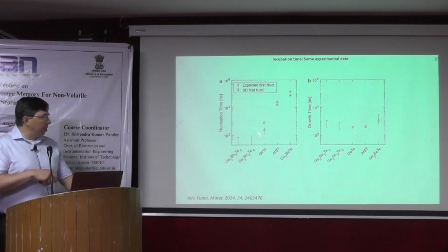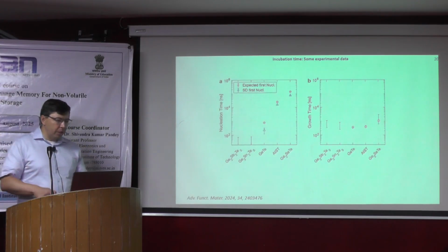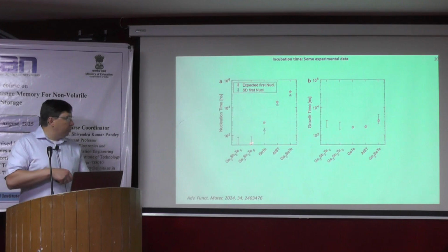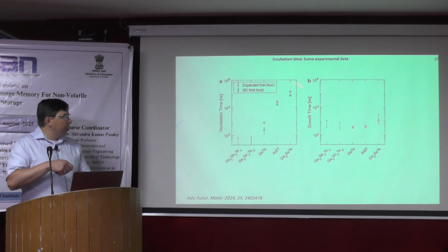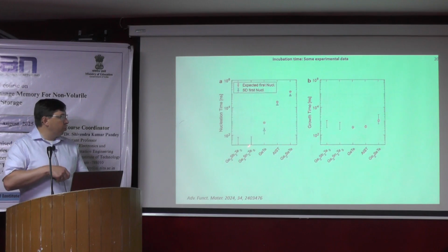So the nucleation-dominated materials can also be much faster regarding the crystallization, even faster than the growth-dominated ones, because you need a longer time first to make a nucleus and then to allow these materials to grow.